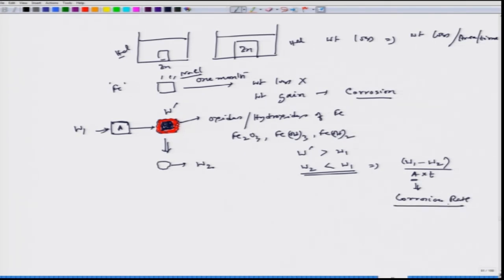Fine. So, that means what we have gained from this particular lecture is we need to consider corrosion rate in the form of loss of metal, per unit area, per unit time, and area is important factor for the normalization, because the surface reactions are leading to the dissolution of metal, not the bulk of the system.